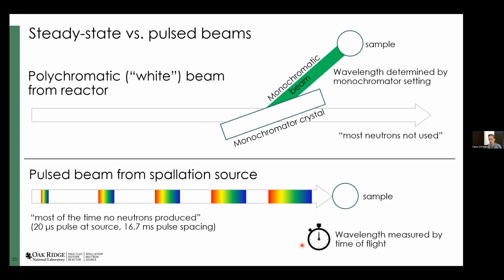At a pulse beam, you use a very different technique because the velocity at which neutrons travel depends on the wavelength. If you come with a very sharp pulse, as this pulse travels to your instrument, it will spread out, and the high energy neutrons will come first, and the low energy neutrons will come later. And so we can shine all of that onto our sample and measure time of flight of when the neutrons arrive, and from there know what wavelength that neutron had.